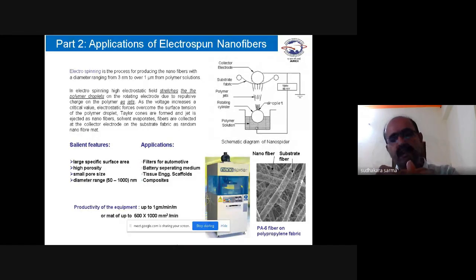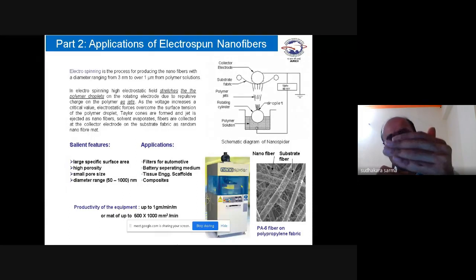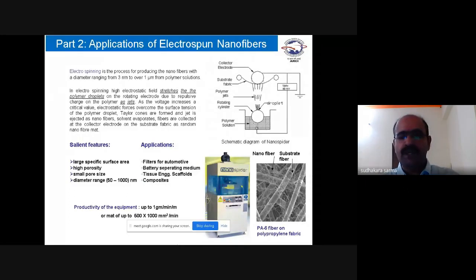We coat these nanofibers on substrate material, for example, polypropylene fabric. On that we coat these nanofibers, and nanofibers are collected onto the substrate. You can see the SEM images of the nanofibers coated on the polypropylene fabric. Here the polypropylene fabric has micron size fibers, around 30 microns, whereas the nanofibers are around 200 to 500 nanometers. We can see the small fibers. These fibers are produced from this Nanospider.